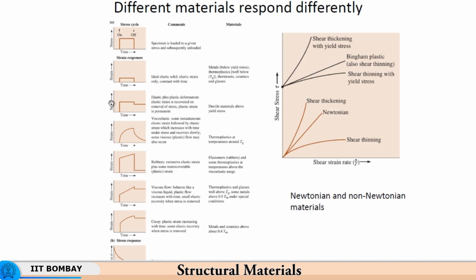Here you have an elastoplastic solid, where the difference is that the elastic strain is partly recovered. It is not fully recovered, it is partly recovered, and there is some amount of plastic strain that is retained. So, some elastic strain is always there, and then there is plastic strain retained by the material. So, permanent deformation is present, and so these are ductile metals above the yield strength of the material. So, essentially this is the kind of response.